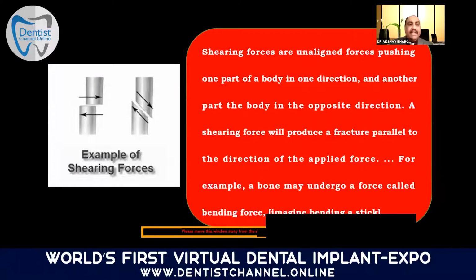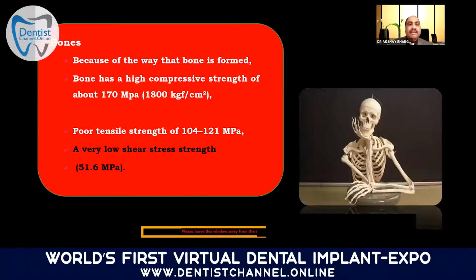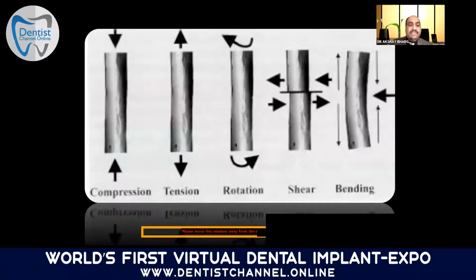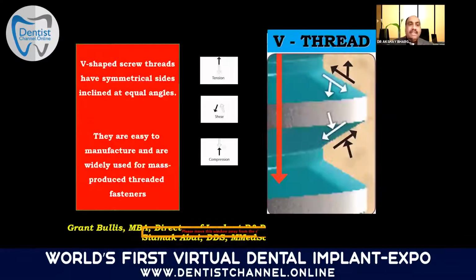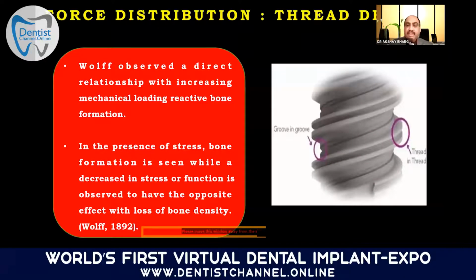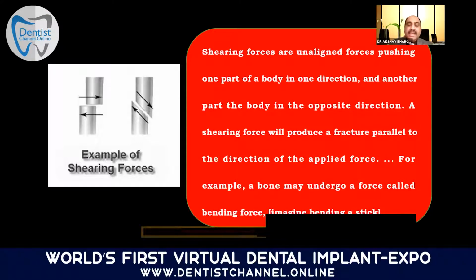Now, I will come back to the slide again. Bones generally have a very good aptitude to take high compressive strength, about 170 MPa. They take poor tensile strength and very low shear stress, which, if you saw even in 1995 when we did the study, we found that horizontal stresses are not taken because the bone can't take the tensile strength or the shear stress. So these are the types of forces that you see: compression, tension, rotation, shear, bending, etc. Now coming back to the slide which I missed, shearing forces generally are horizontal forces, which when you apply, they create a bending force.